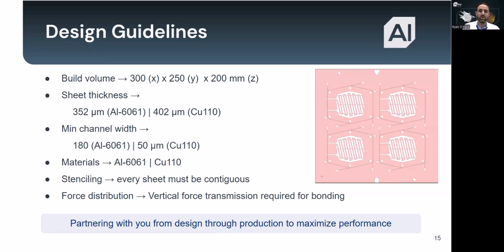One design rule worth noting is that each sheet layer has to remain structurally continuous for bonding, and force distribution is important. Since we're diffusion bonding sheet by sheet, vertical force transmission is required to achieve monolithic bonds. The bottom line: these are practical boundaries, but they're also enablers. Within these limits, we can create geometries that maximize thermal performance.